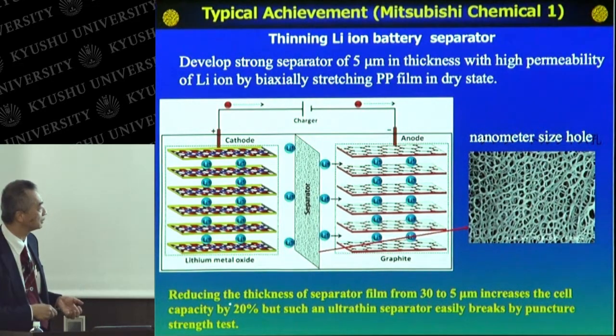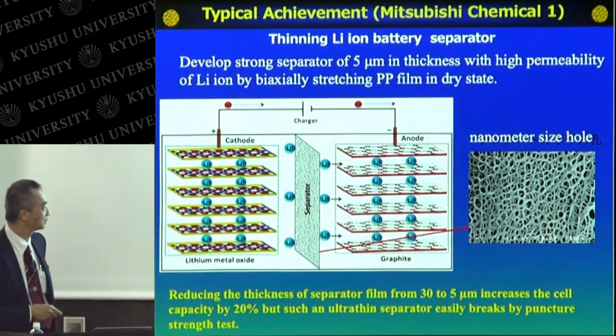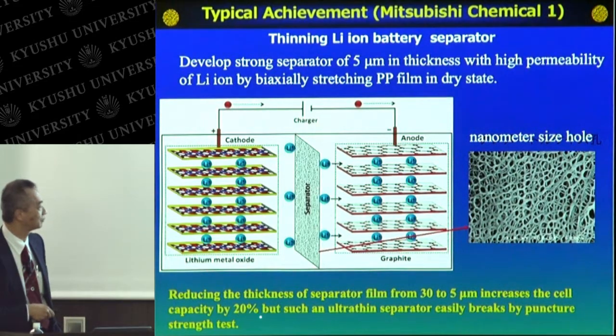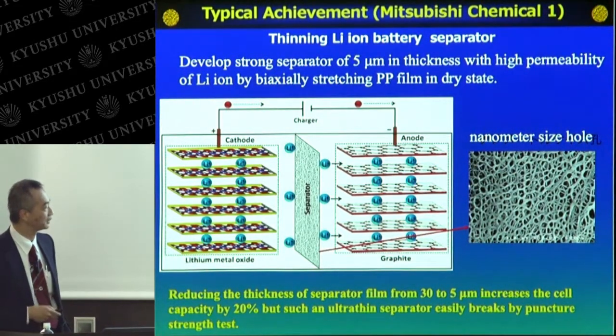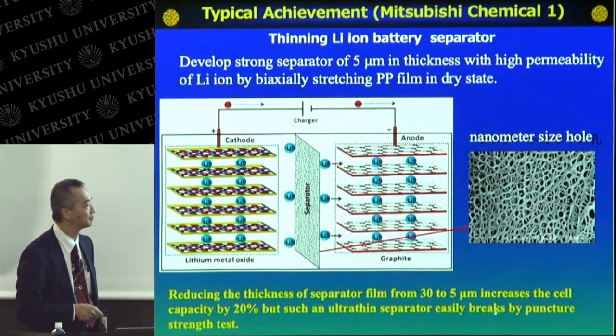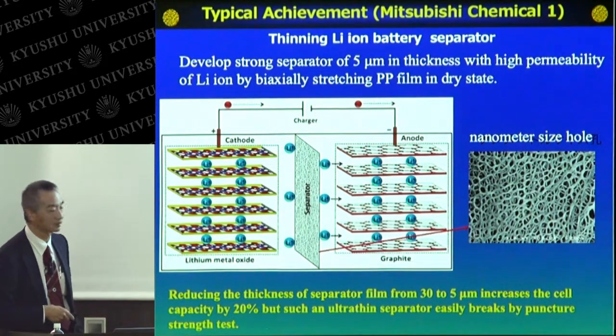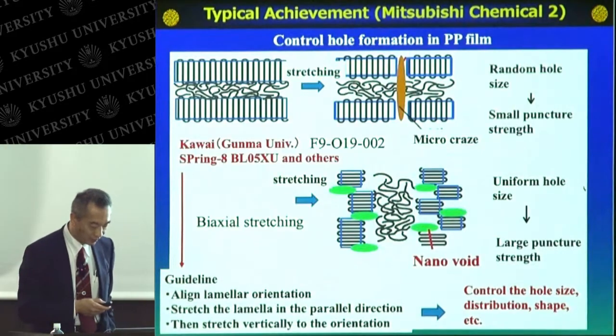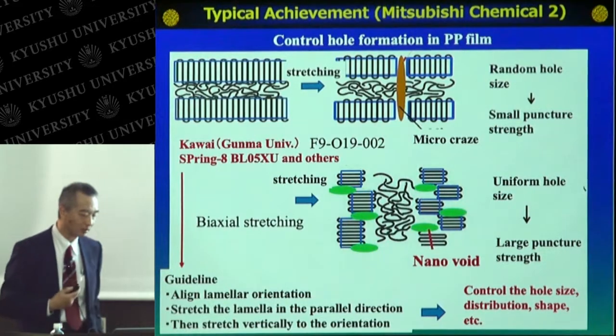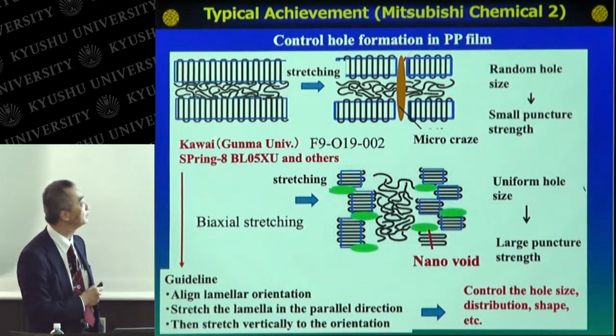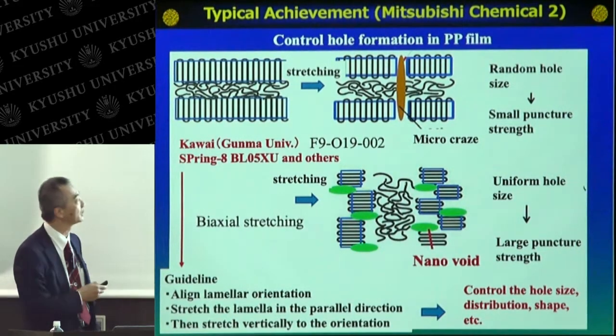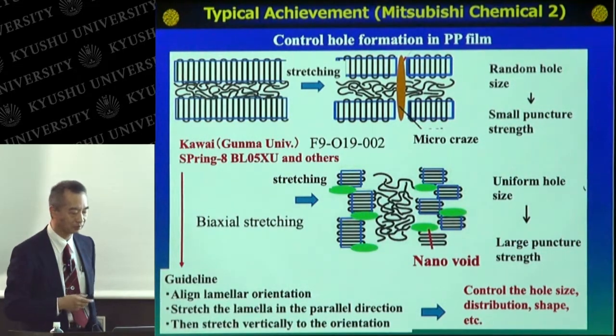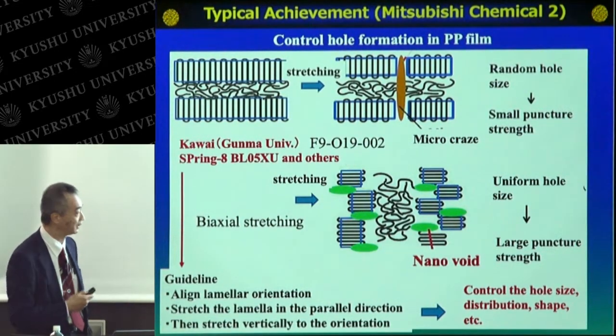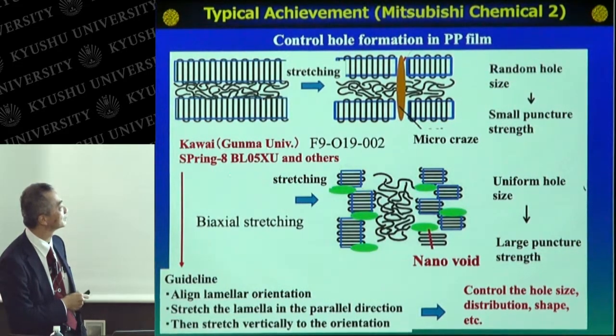Mitsubishi Chemical's target is reducing the thickness of the separator film from about 30 to 5 micrometers, which increases the cell capacity by 20%. But usually, such an ultra-thin separator easily breaks in the puncture strength test. So they collaborated with Professor Kawai at Gunma University, and they used the SPring-8 beamline. Our program can use this beamline almost freely.